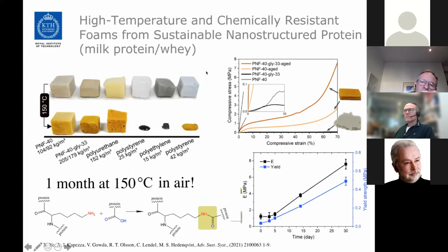What we also observed recently, and recently published, is that proteins, for example in the form of foams, are actually improving their properties in very harsh conditions. Here is a comparison of the different foams that we started with from the beginning. Then we treated the foam in a very harsh environment, up to 1 month at 150 degrees in air, a very, very harsh condition. If you consider polyethylene or polystyrene foams, they immediately melt, of course, and then degrade within half a day or 2 days. The polyurethane sustains the environment better, but polyurethane is very bad in terms of fire properties as compared to, for example, proteins.